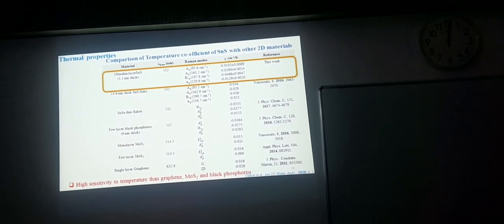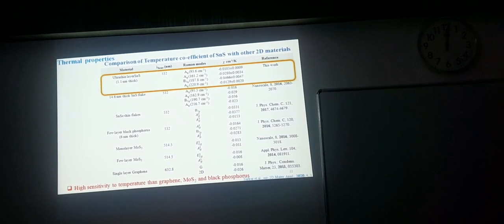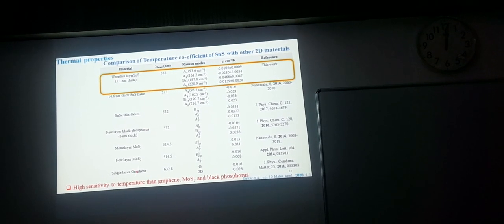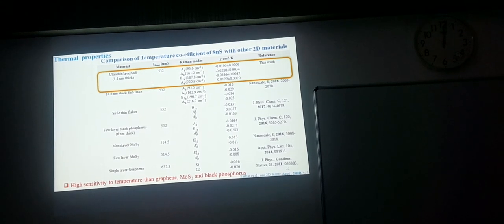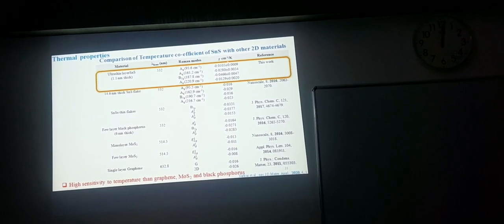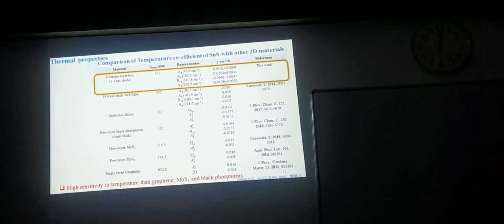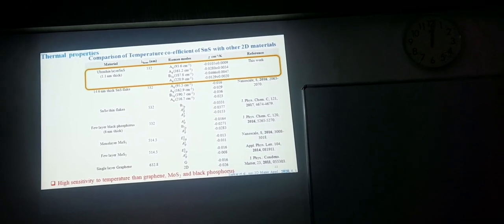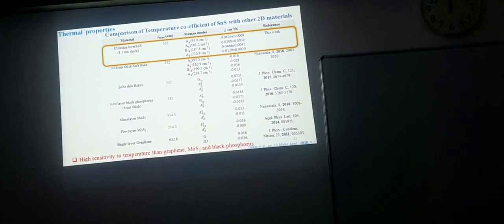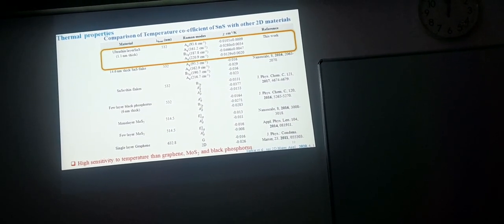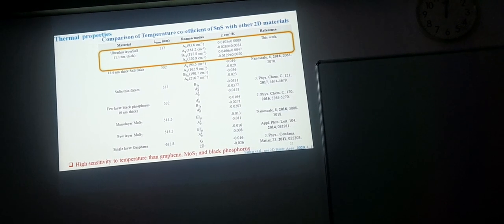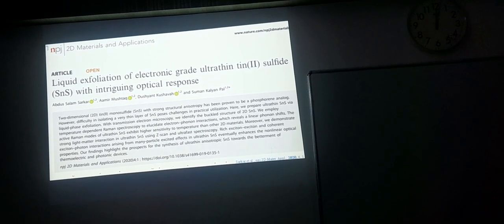But the important thing I just want to show you is, if you consider other two-dimensional materials, especially graphene, MoS2, or others, the temperature coefficient here is very high, which is very important for, let's say, thermoelectric application, where thermal energy is converted to electricity. Not only that, we have also focused on nonlinear optics. I am not showing it here, that is Z-scan, and we also found a very high saturable absorption coefficient in this SnS system, which was actually published in Nature in 2020.